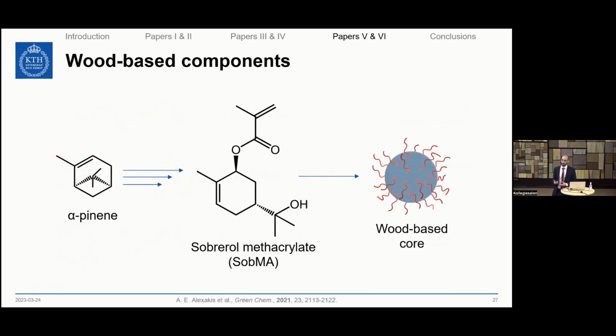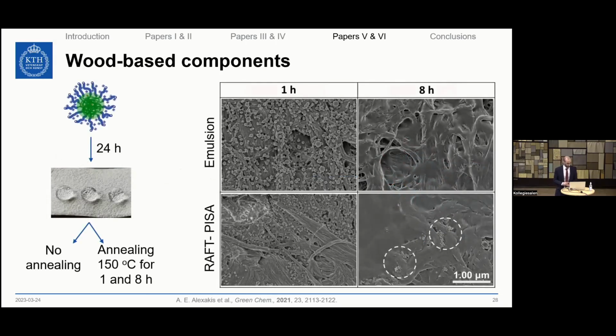In order to address these sustainability development goals and trying to move away from these fossil-based resources, we tried to utilize wood biomass. So we focused on the wood-based and hydrophobic core, and we used the terpene-derived or alpha-pinene-derived sobrerol after a short methacrylation that we performed. We were able to prepare spherical nanolatexes both by using a Malmström polymerization, where we used a low molecular weight surfactant, and also by using RAFT-mediated PISA, where we used a higher molecular weight macro-RAFT agent.